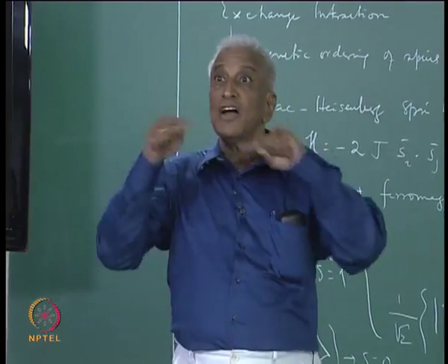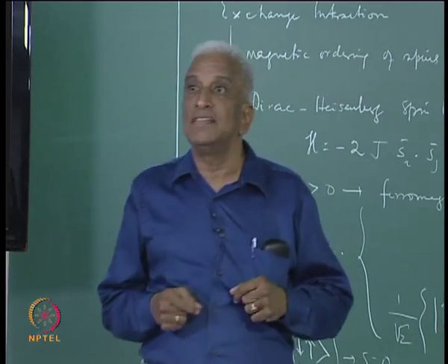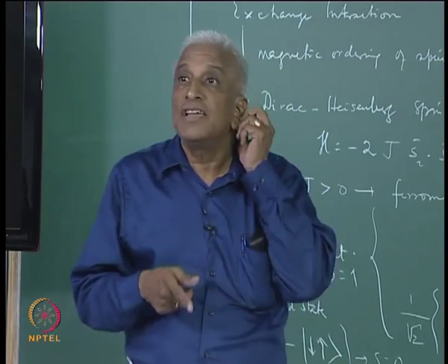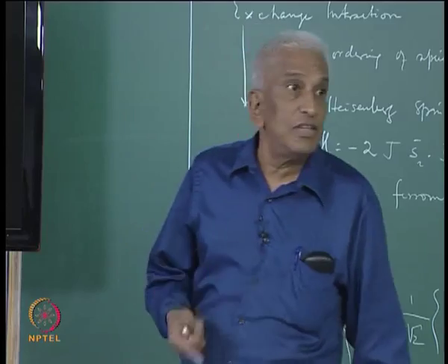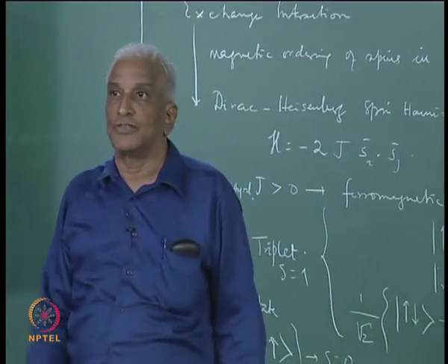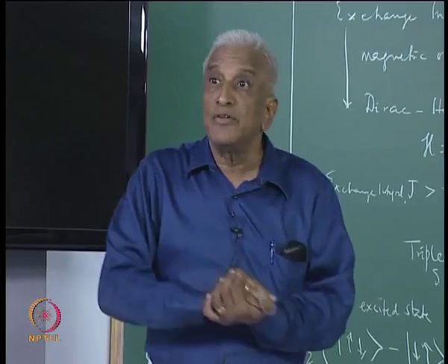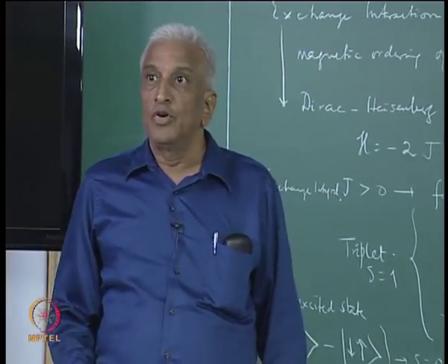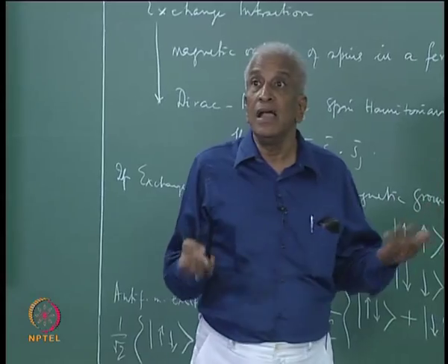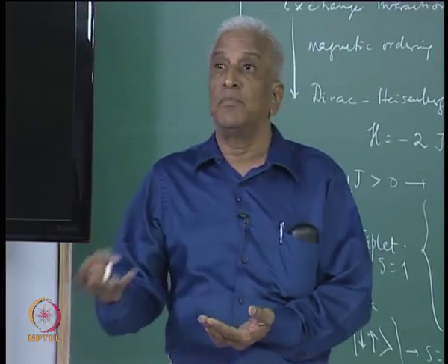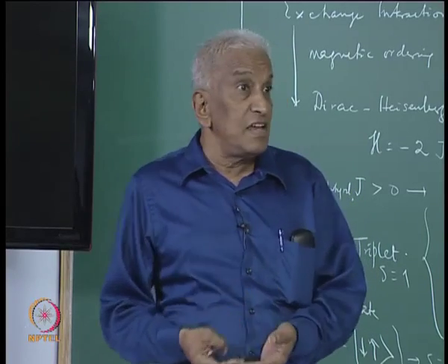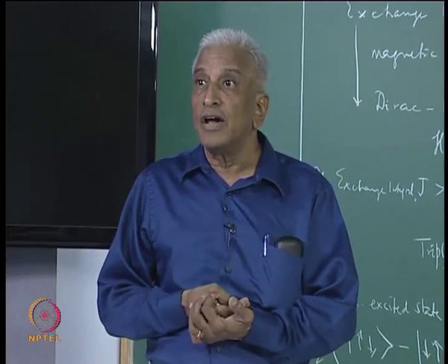But if the ions are magnetic ions, then the amplitude of the wave reflected from the A ions plane will differ substantially from that of the plane of the B ions because of the additional magnetic scattering contributions. They depend on the angle between the spin moments of the ion and the incoming neutron beam. So, the destructive interference will then be incomplete, and therefore, you get a diffraction line at that particular angle. Whereas, even though the ions are magnetic, if we are above the Néel temperature where there is no order, then they will not give this extra line.